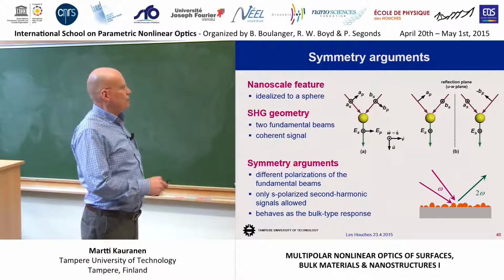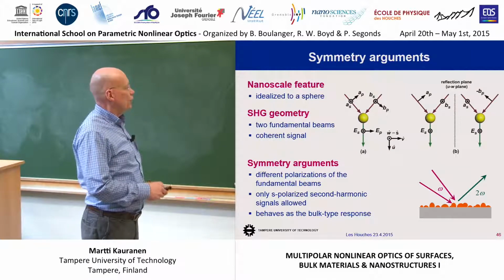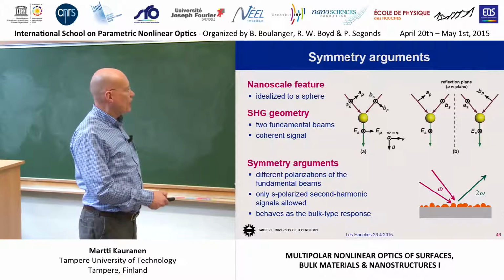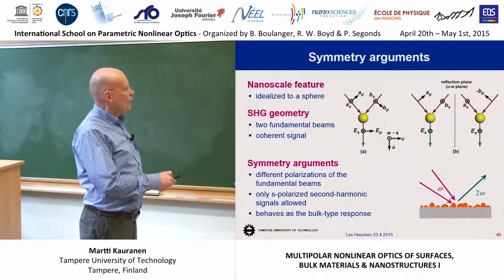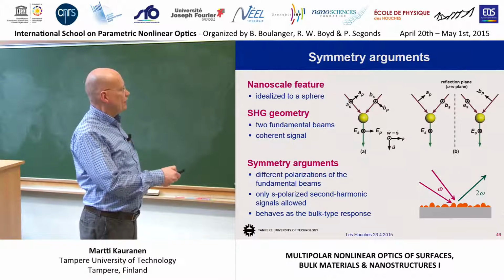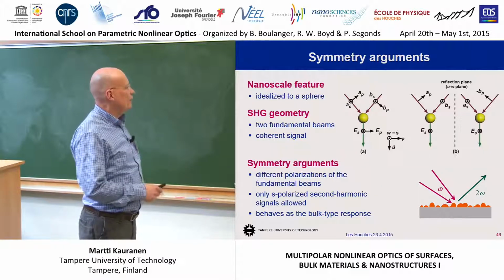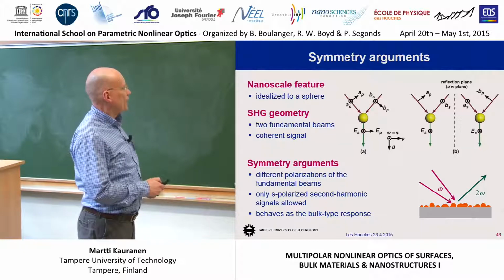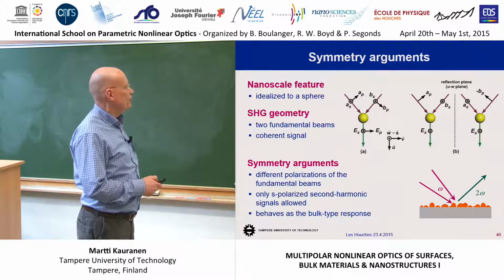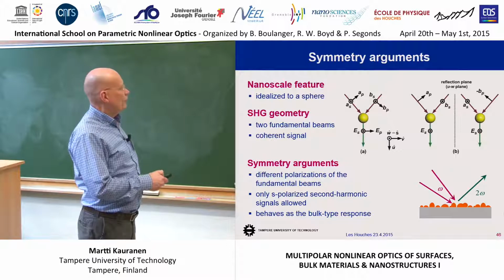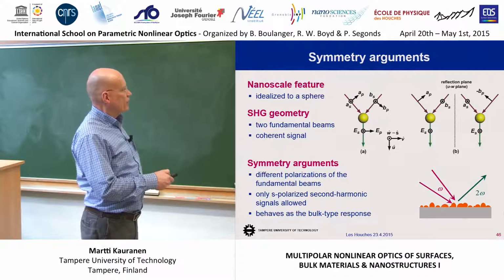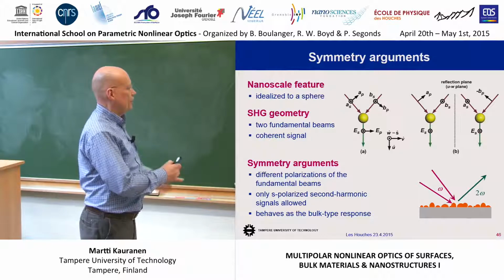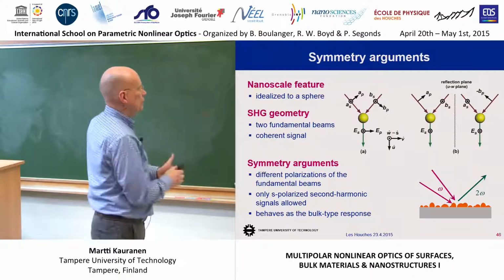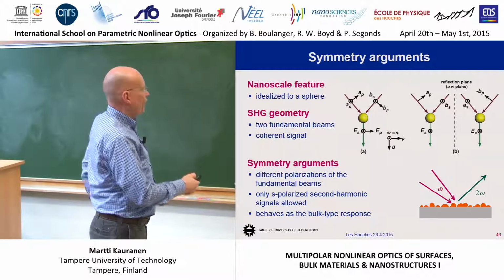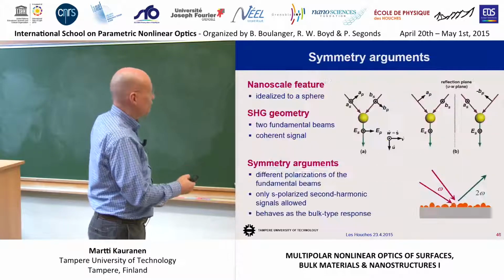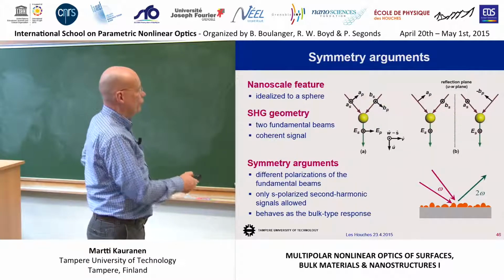And we built sort of a symmetry argument for this. We idealized this bump into a sphere, and then we brought in these beams like this, a signal is going this way, and then when you look at this experimental geometry, when you forget the states of polarization of the beams, you have a mirror plane here. I mean, this plane is a mirror plane, and then the plane of the board would be a mirror plane.